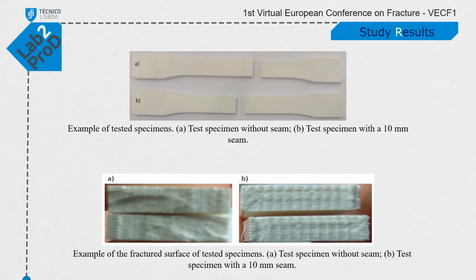Samples manufactured without a seam continued to sustain the applied load, undergoing plasticity, denoting the tearing of the extruded paths, while in samples with seam, rupture of the specimen is coincident with the elastic limit of the material, the surface is uniform, and separation of paths that were deposited with different printheads seems to be present.